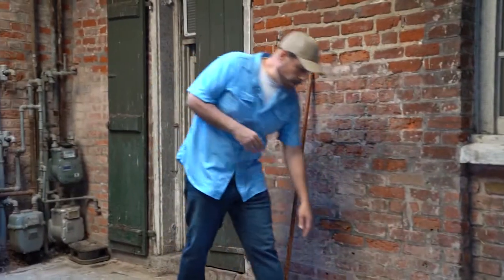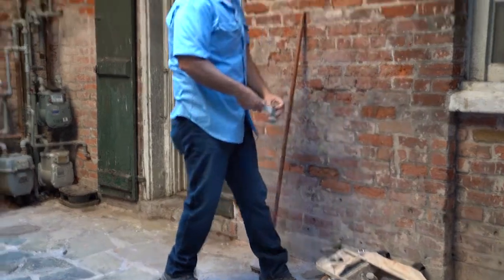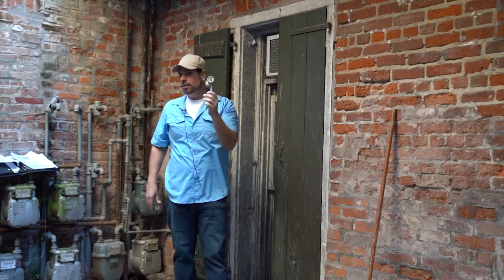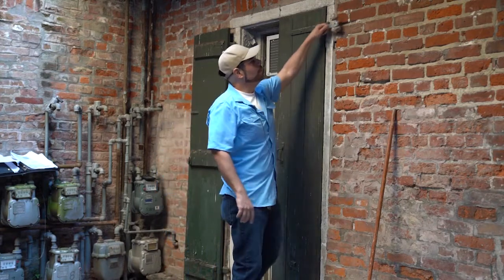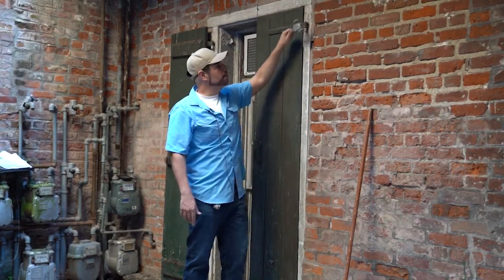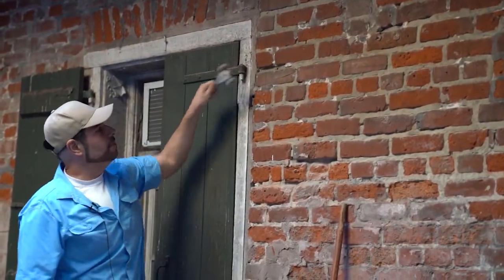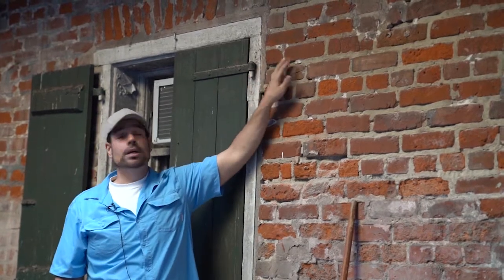As professionals, what can we do? Once we have ripped out our mortar joint, in some cases we're fortunate enough to use this breaker — it looks a lot like a roller skate with wheels on it, and this is a masonry nail on the end. You wouldn't want to use this to hammer studs into your wall, but for raking out masonry joints it does just a fine job. We can break this joint out nice and easy. We want a clean top and a clean bottom on the edge of our brick and a uniform base for our new mortar to stick to. That's about an inch or an inch and a quarter inch deep — you want to be between an inch and an inch and a half for this to be a structural repair.